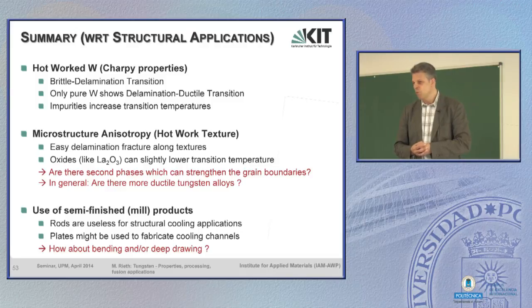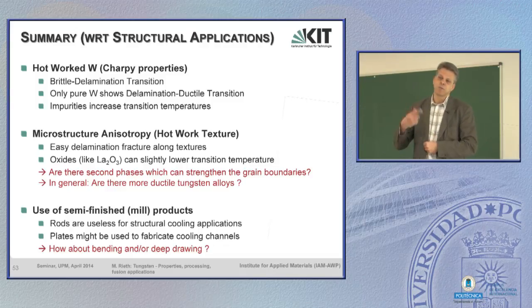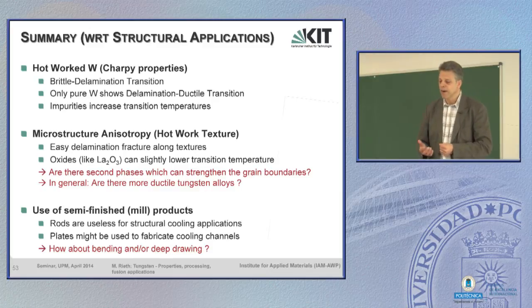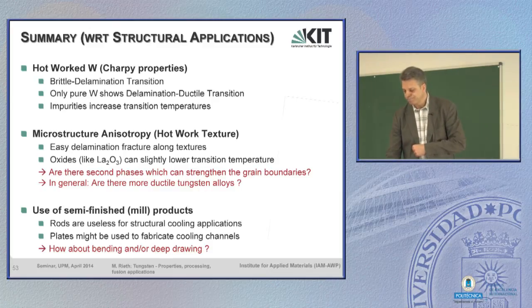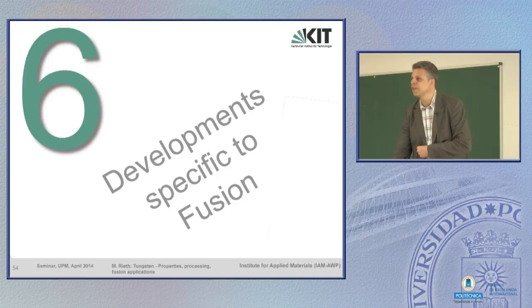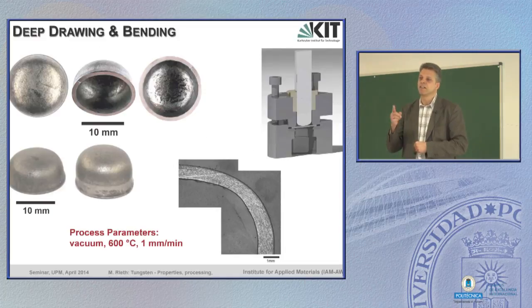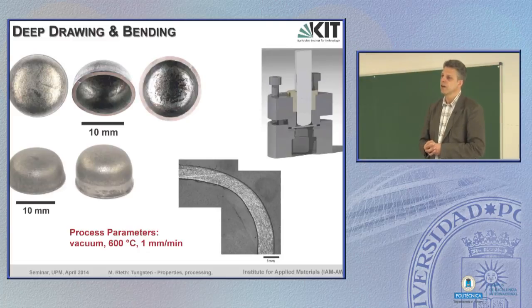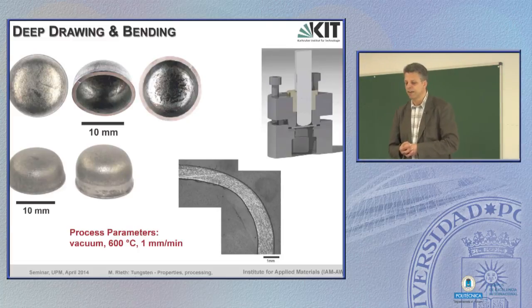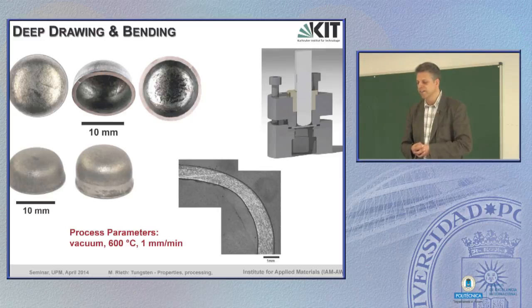And well, if you work with plates, then an immediate idea, namely deep drawing or bending, comes into play. And this is part of some very specific developments in fusion technology. We have tried to fabricate these fingers for the divertor application I have shown at the beginning by deep drawing, and indeed, you see, it is more or less feasible. However, it needs